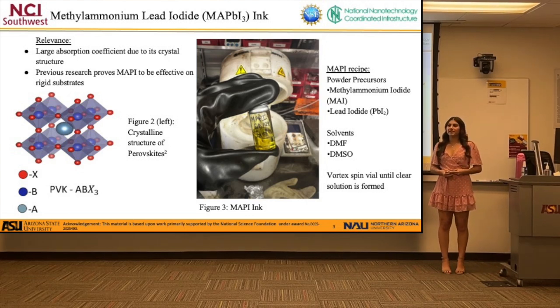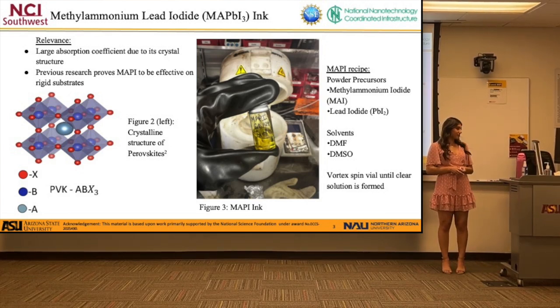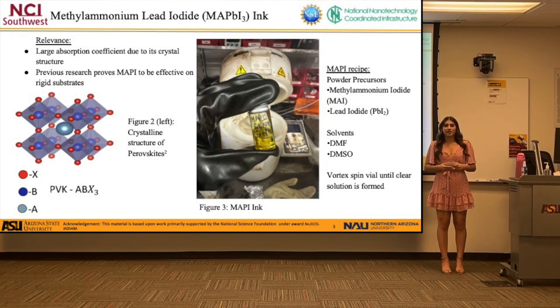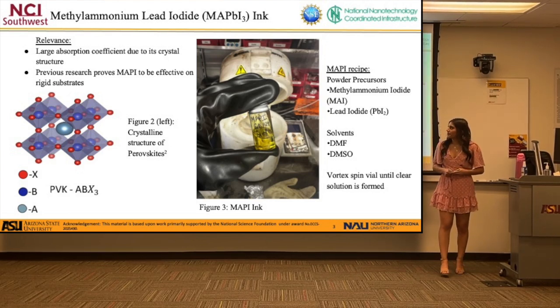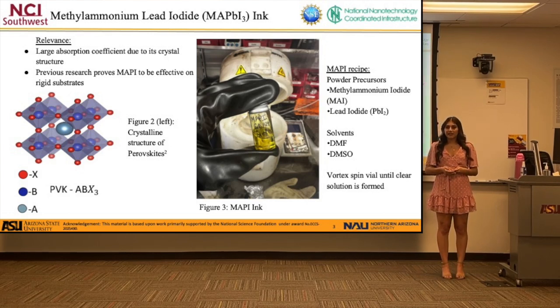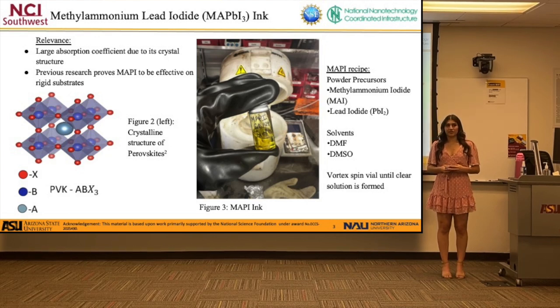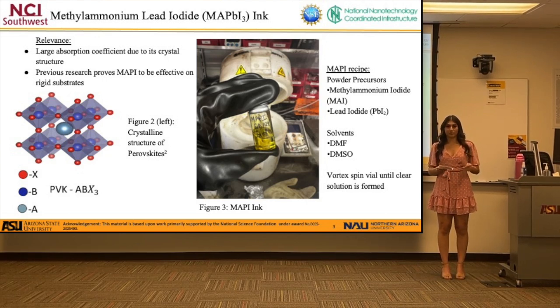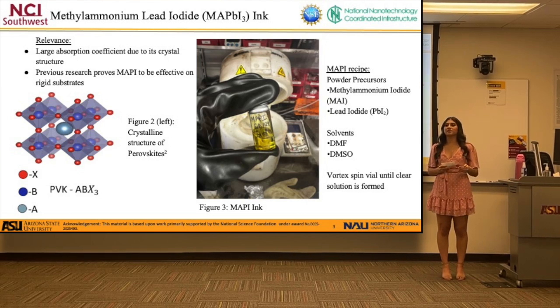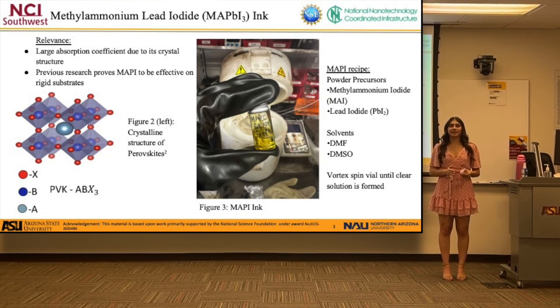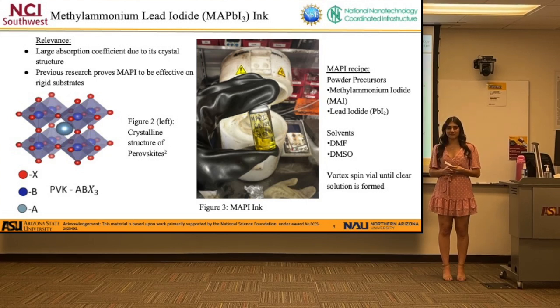So the specific perovskite that I used within this research is called methyl ammonium lead iodide, also known as MAPI ink. The relevance of using this specific perovskite is because it has a large absorption coefficient due to its crystal structure. You can see its crystal structure in figure 2. And the relevance of it having a large absorption coefficient is because it can maximize the current output. Previous research demonstrates that MAPI proves to be effective on rigid substrates, so we are hoping that it is the same on flexible substrates with minor adjustments.